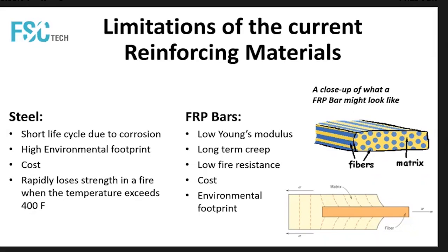They normally have long-term creep, and that happens basically because of how the composite is actually made: you have a bunch of strands, the fibers, that are embedded in a matrix. When you are casting that kind of rebar into a concrete casting, like in a pre-stressing application, the shear is going to the external skin of the bar, and the central area where you have fibers is transmitted to those fibers only by the tangential modulus of the resin, which is extremely low.